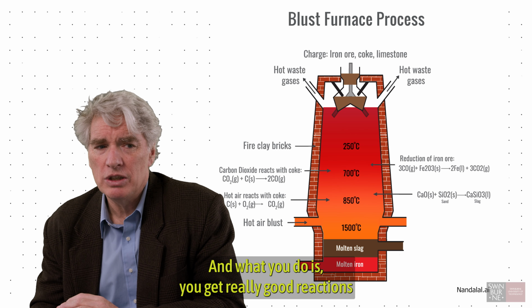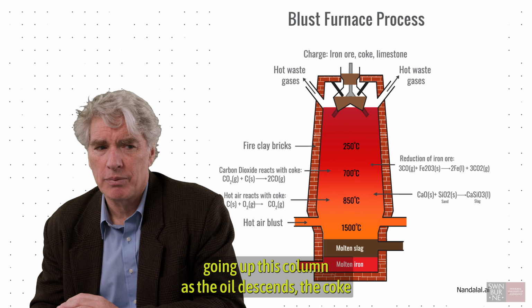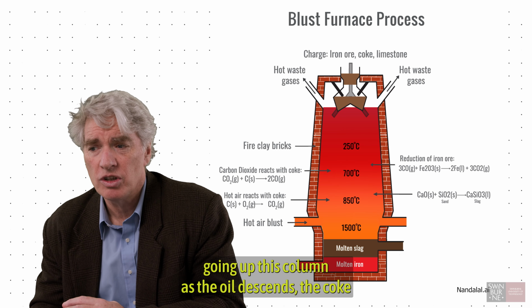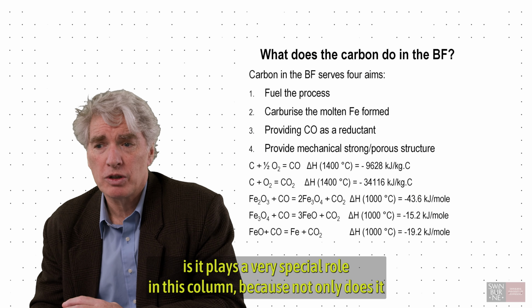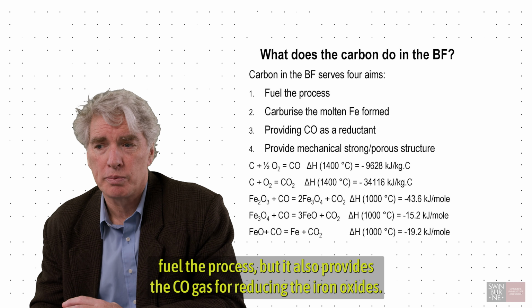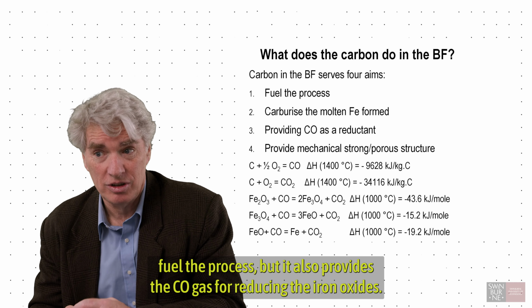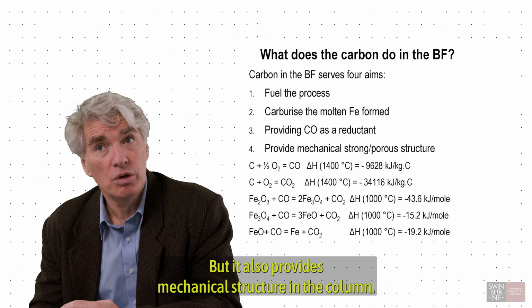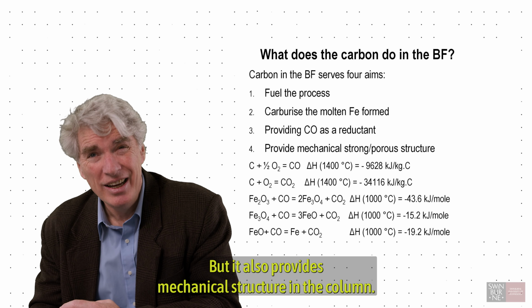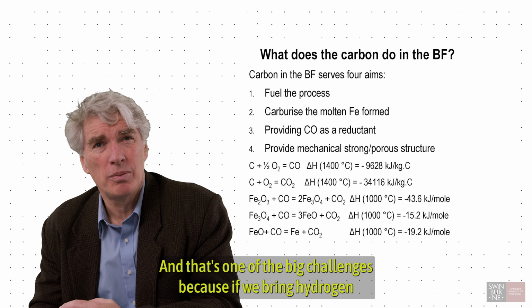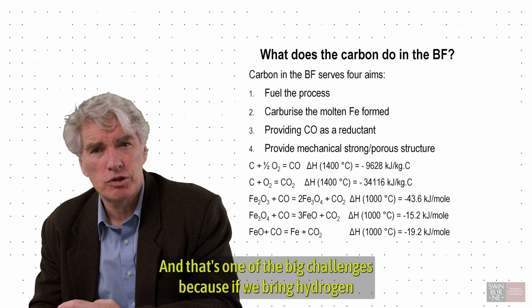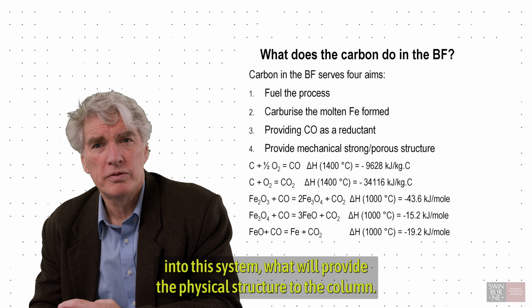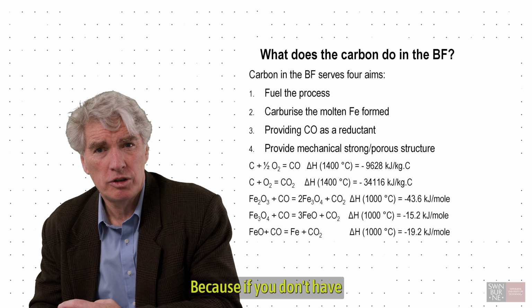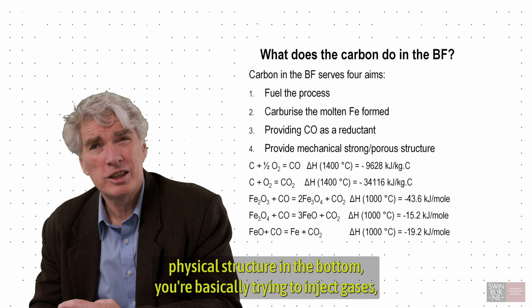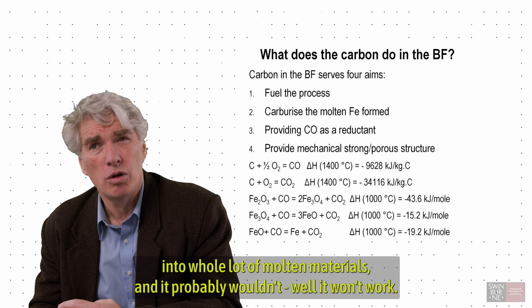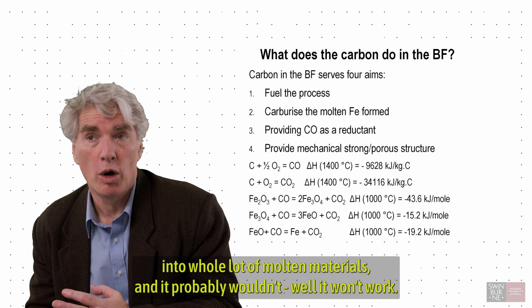And what you do is you get really good reaction going up this column as the ore descends. The coke plays a very special role in this column because not only does it fuel the process, but it also provides the CO gas for reducing the iron oxides. But it also provides mechanical structure in the column. And that's one of the big challenges, because if we bring hydrogen into this system, what will provide the physical structure to the column? Because if you don't have physical structure near the bottom, you're basically trying to inject gases into a whole lot of molten materials, and it probably won't work.